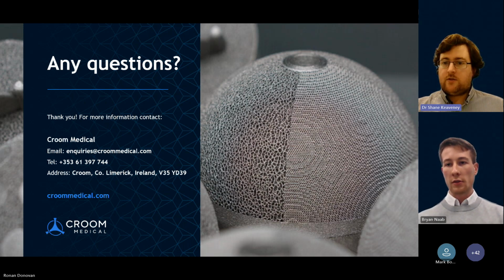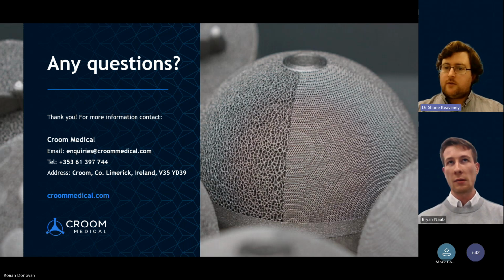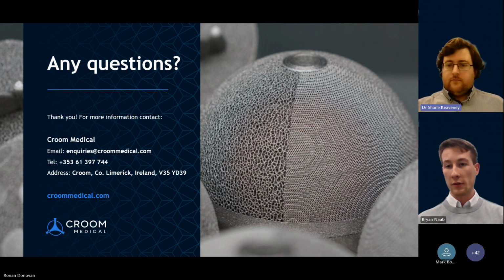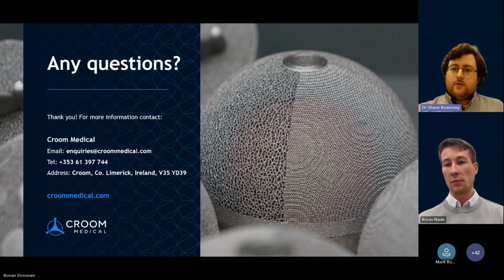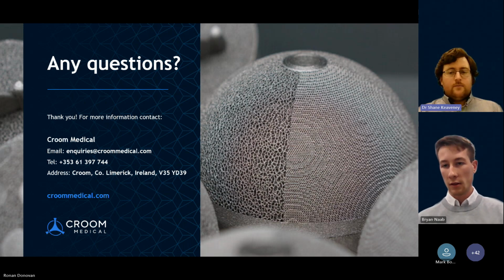So I would say if you're just trying to investigate the base material's performance, I would always do it in as-machined state or even actually as polished. I think the ASTM standard actually calls for a surface roughness of less than 0.2 micrometers Ra. So you would actually need to polish your sample if you want to adhere to that standard. Now, when it comes to more of an upscale, full-scale component test, of course, you would keep it in that rough surface condition or whatever condition you're planning to implant your device in. So yeah, it really depends on which type of fatigue test you're talking about.